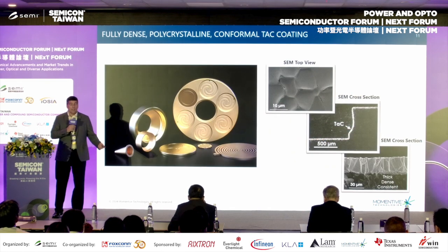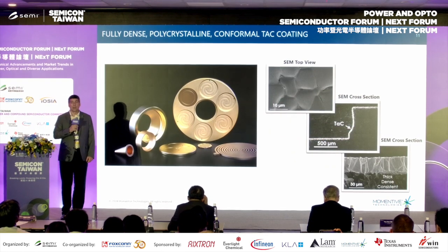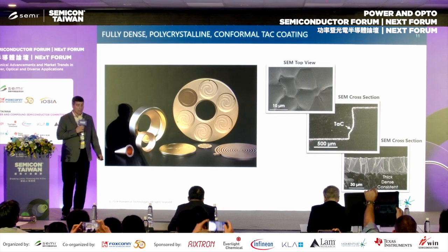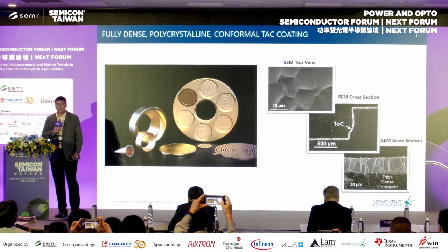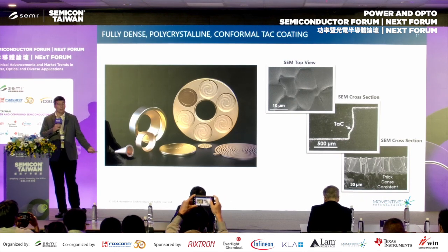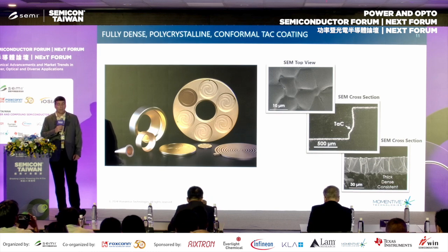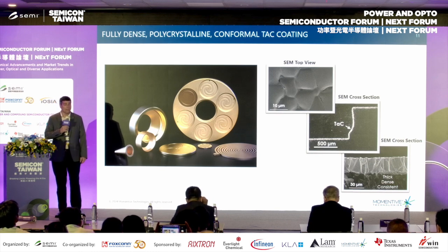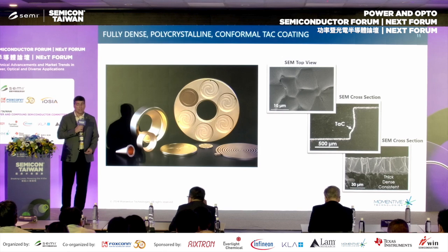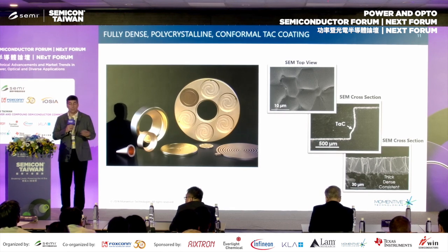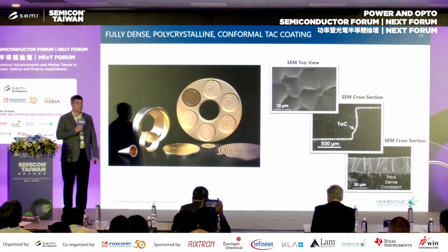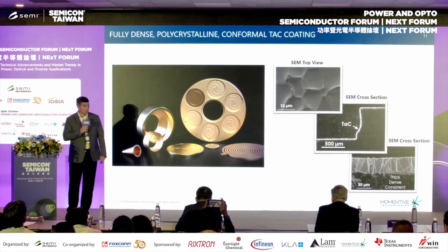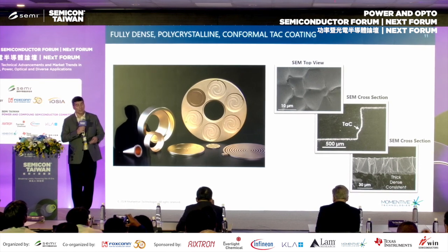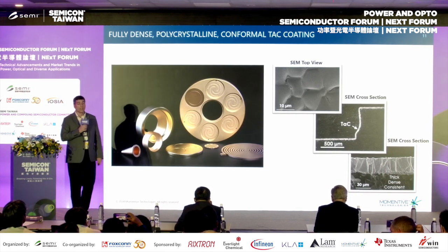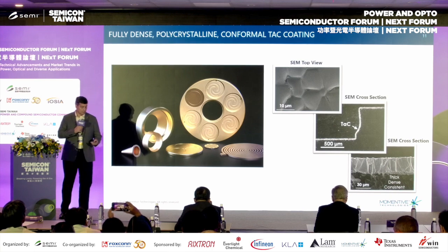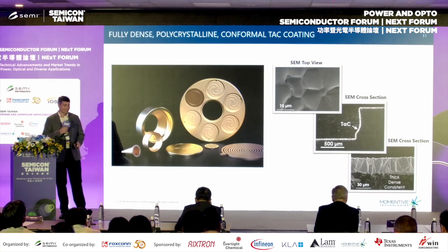So the answer for that, in our view, is the tantalum carbide. The tantalum carbide that we produce and sell is a fully dense polycrystalline conformal TaC coating. It effectively protects the underlying graphite and prevents contamination of the crystal, whether it's Epi or PVT, by the graphite. You can see some of the images here showing some of the cross sections as well as the nice conformal nature of the tantalum carbide. Plus it's pretty, right?